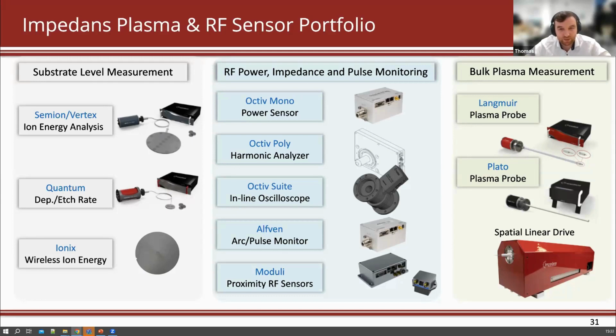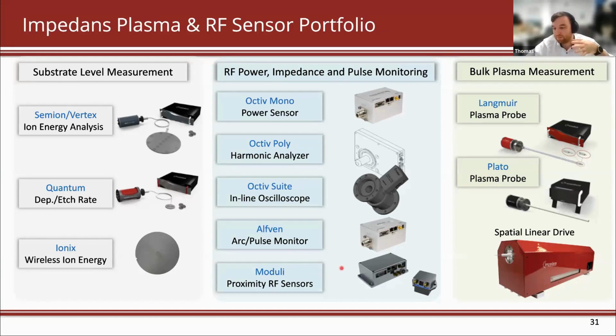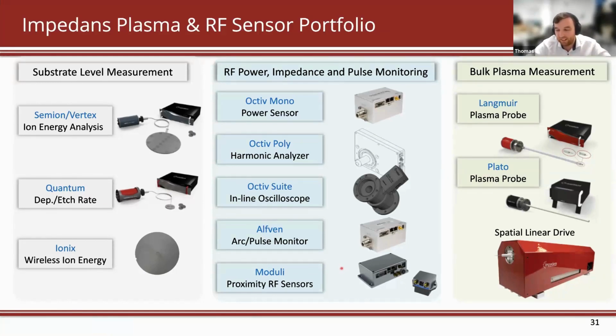How do we decide the bias frequency? It's a good question. So you want to use the lowest frequency possible, basically, because the higher the frequency you use, the more the high frequency couples well into the plasma. I actually don't have frequency versus results in this presentation, but as a rule of thumb, if you want to control plasma density, you use the higher frequencies, okay? Because you get the most inductive coupling, which is more efficient at generating plasma, whereas at the low frequencies you get more capacitive coupling. So even if you're in a CCP, as you operate at higher frequencies, you actually have quite a large inductive component, and the inductive component makes it like an ICP. You get much more dense plasma. So higher frequencies more inductive, lower frequencies more capacitive. So you want to use low frequencies for that.